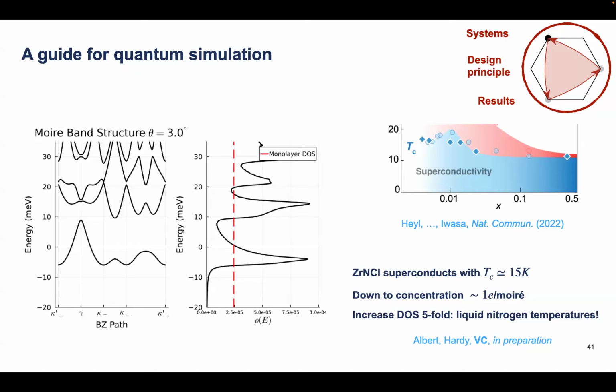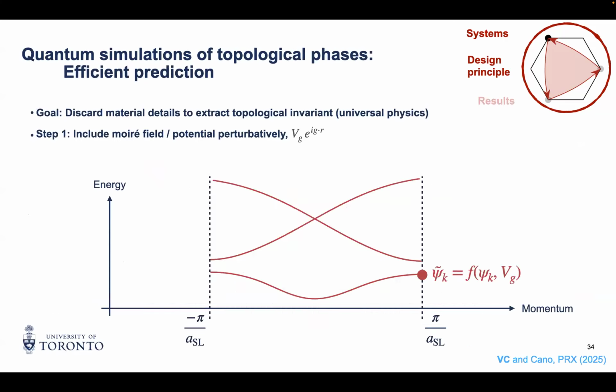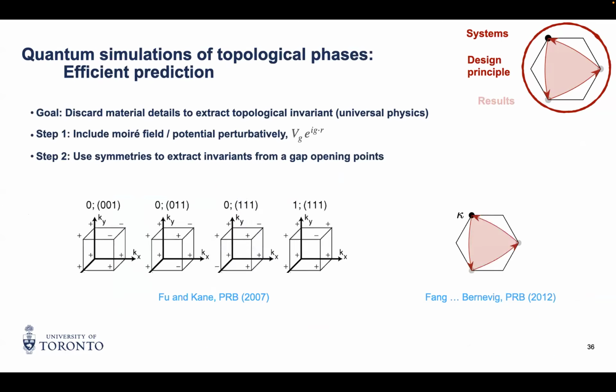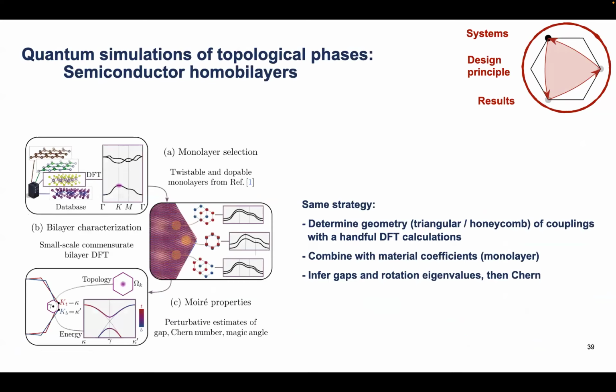Different atoms, like different materials, play a role here. This is abstracted out in our DFT. So the different atoms, how they play a role on the microscopic scale, is just how big is that tunneling. If the atoms don't like to be on top of one another, they will go further away, and that tunneling will be smaller. So the atoms you manipulate basically change the geometry of your coupling on the moiré scale. It's interlayer here; we also have intralayer components. So the chemistry is in the harmonics of the superlattice potential, basically.